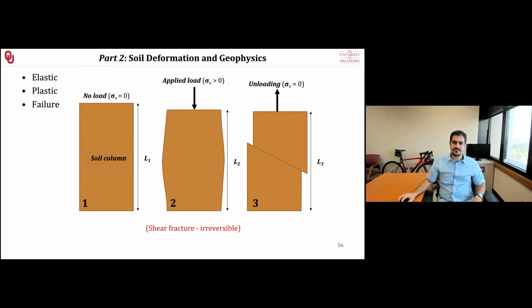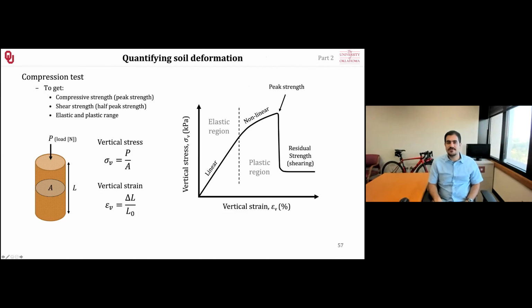That's the shear fracture. We can quantify this deformation in the lab with confined compression or unconfined compression test. In here, I'm just going to go with the unconfined, for instance. What we do, we gradually increase the load or the stress on the soil and measure the changes in its length. If we plot this, we will have a linear part which will tell us the elastic region. It tells you that if you remove the load, you will retain the same shape that your column had initially.